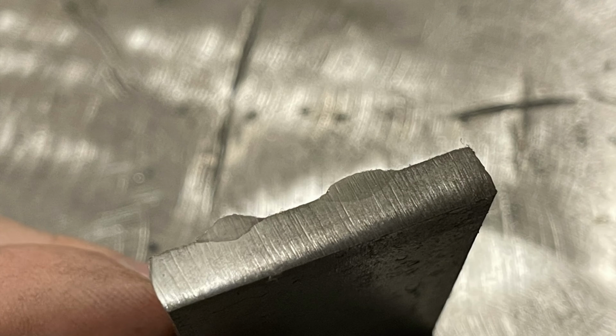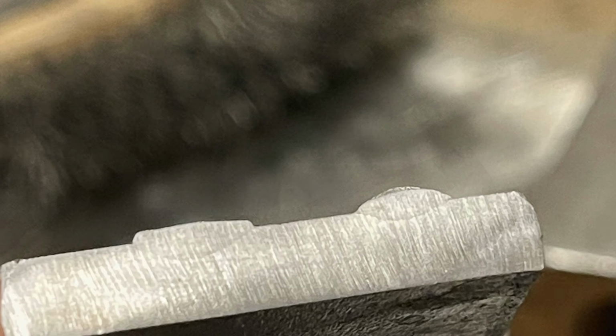So let's take a look. I'll actually put these back to back, and I'll put a high detail up now so you can see what I'm seeing. Now, if you look at these, we can see that the E7018 has pretty shallow penetration beyond the plate, and that's to be expected. The E6010, without a doubt, has more penetration beyond the plate. And this is kind of a small scale test to show you the difference in arc force.